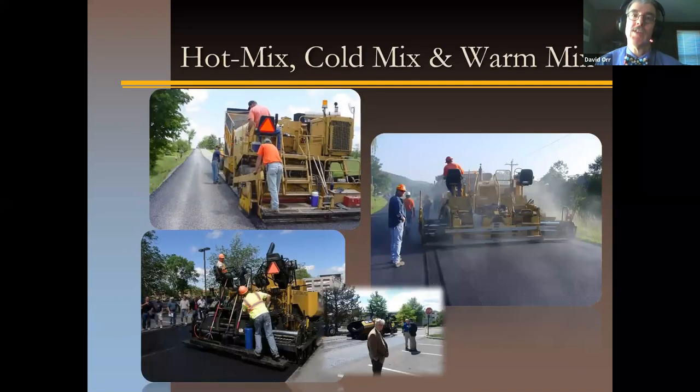Now, let's talk a little bit about the mix types. Hot mix, cold mix, and warm mix. We make them hot, cold, or warm because what we're really trying to do is take a product, asphalt, which is pretty solid at room temperatures, even up to 147, it's at best sticky. We're trying to make it liquid enough to coat the rocks and hold the rocks together. So we have to heat it up in some way or make it liquid in some way. With hot mix, we do that by heating it up to